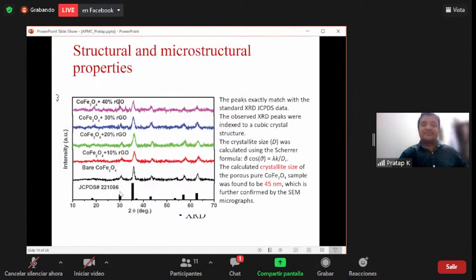These are the structural characterizations. The black one is pure cobalt ferrite, the red one is cobalt ferrite with 10% RGO, green is cobalt ferrite with 20% RGO, blue or purple is cobalt ferrite with 30% RGO, and this color is cobalt ferrite with 40% RGO. Here, the peaks have exactly matched the JCPDS data. The observed crystal structure is cubic, and the crystallite size is calculated using Scherrer's formula, D equals K lambda by beta cos theta. The calculated crystallite size of this porous sample is found to be 45 nanometers. When we check the SEM, it is almost the same, so SEM has confirmed the calculated crystallite size.